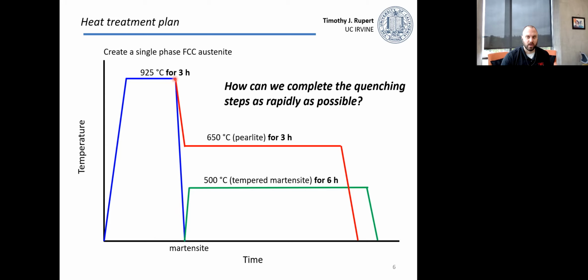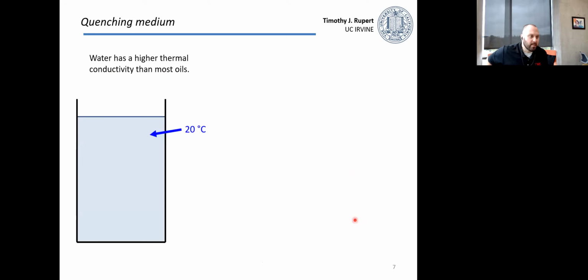So we want to not allow any of those transformations that the phase diagram predicts to happen. So we really need to rapidly quench it down as fast as possible. We want this curve right here to be as close to vertical as possible. And that's also generally true for after we do our pearlite and tempered martensite annealing treatments. We want to very rapidly quench these down and have a really high slope at the end. Okay. So we need to think about doing that.